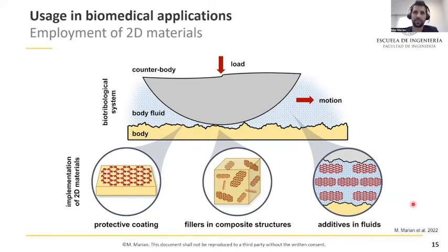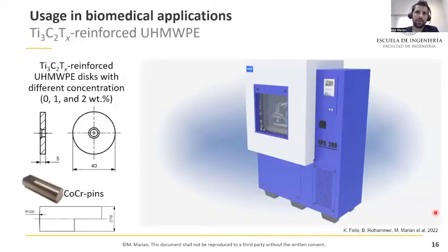However, what we can state is that MXenes have very rarely been studied in a biotribological context so far. So we recently fabricated MXene reinforced ultra high molecular weight polyethylene discs with the aim of enhancing, for example, the biotribological behavior of load bearing implants, such as total knee replacements. The PE powder was mixed with the synthesized MXene powder, filled into press molds, melted and then pressed into shape under pressure and vacuum conditions.